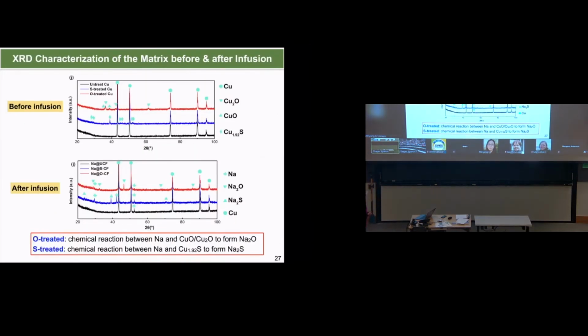The main reason is the chemical interaction between sodium metal and the surface-treated copper foam. For example, for the oxygen-treated one, we find that sodium can actually react with the copper oxide to form sodium oxide during the infusion process. For sulfur, it also forms sodium sulfide. However, the sulfur case doesn't work as well as the oxygen case. Using this method, we are able to very easily infuse a controlled amount of sodium metal into a matrix material. In this case, we can improve the mechanical property of the sodium metal electrode.